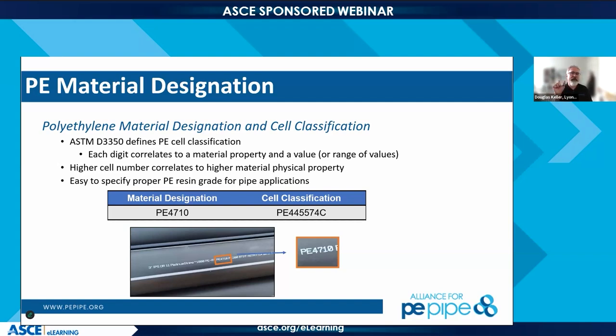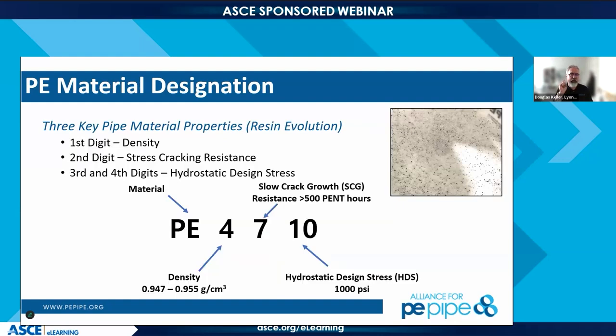And for water applications, it will then be followed by a CC3, which is chlorine categorization. We'll get to that chlorine categorization in a couple of slides. But always make sure you read that print line. Make sure that you're getting what you expected when you ordered that pipe. It will tell you the pipe size, the pipe thickness, and the pressure class. It will tell you when it's made and who made it. And that print line is traceable all the way back to my material through the pipe manufacturer. So if you have an issue, we need to know that print line.